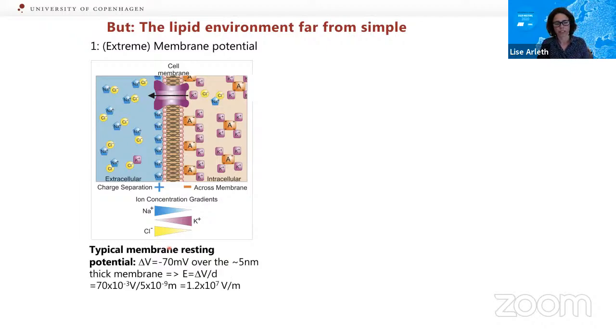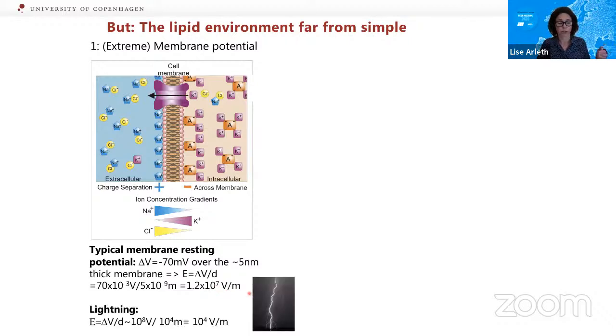If we look at the typical membrane resting potential, it's minus 70 millivolt over the 5 nanometer membrane. This doesn't sound like a lot, minus 70 millivolt, but if we look at the potential drop, it's actually 1.2 times 10 to the 7th volt per meter. If we compare that to a lightning, there we have a potential drop of only 10 to the 4th volt per meter. So this is just saying that it is a quite efficient insulator, this cell membrane here.